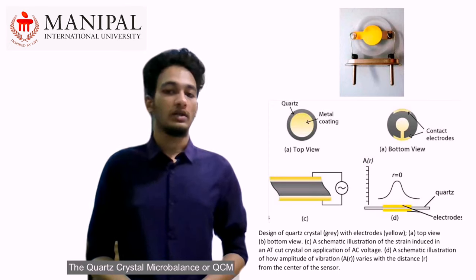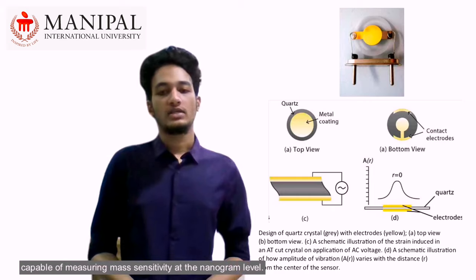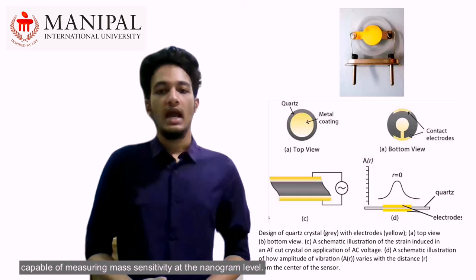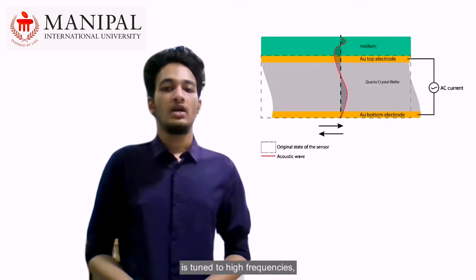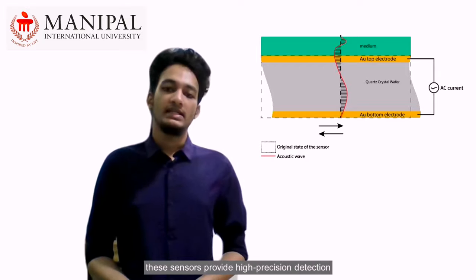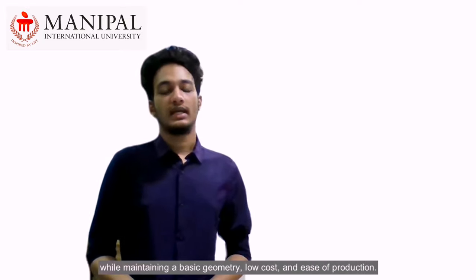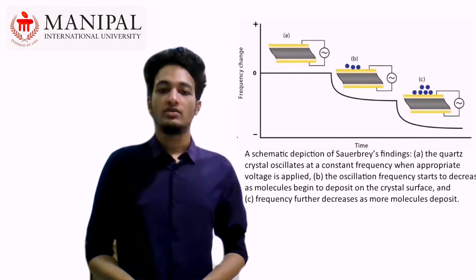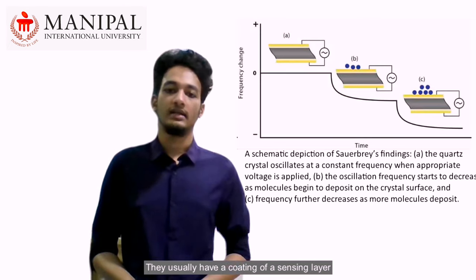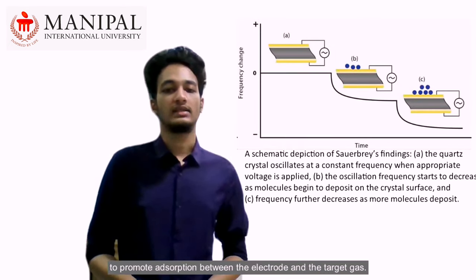The quartz crystal microbalance, or QCM, is a mass detection sensor capable of measuring mass sensitivity at nanogram levels. When a thickness-shear mode piezoelectric crystal is tuned to high frequencies, these sensors provide high precision detection while maintaining a basic geometry, low cost and ease of production. They usually have a coating of a sensing layer to promote adsorption between the electrode and the target gas.